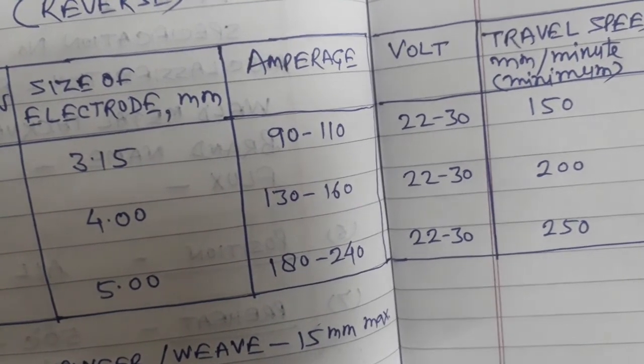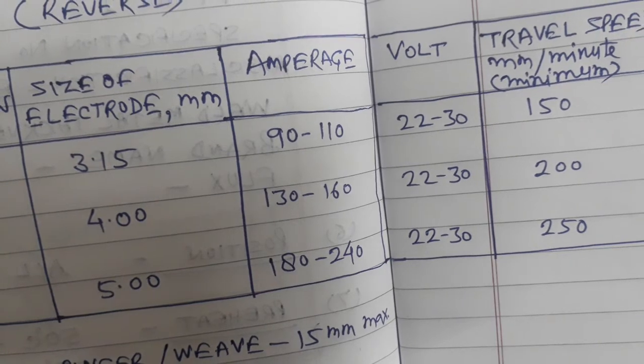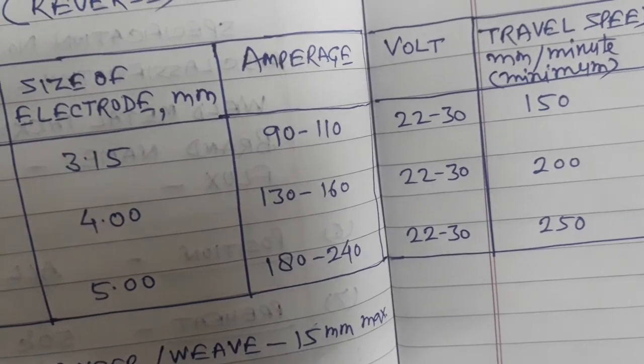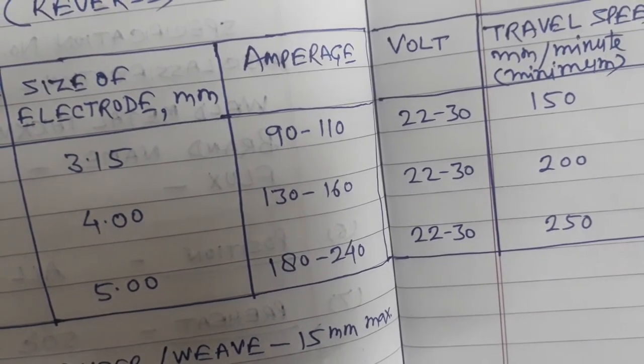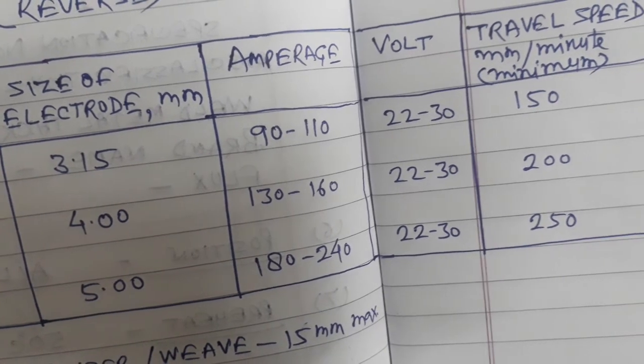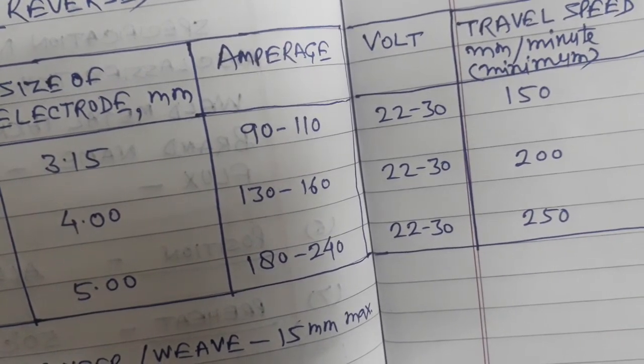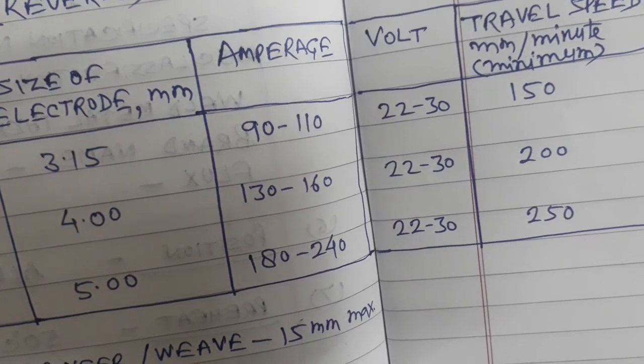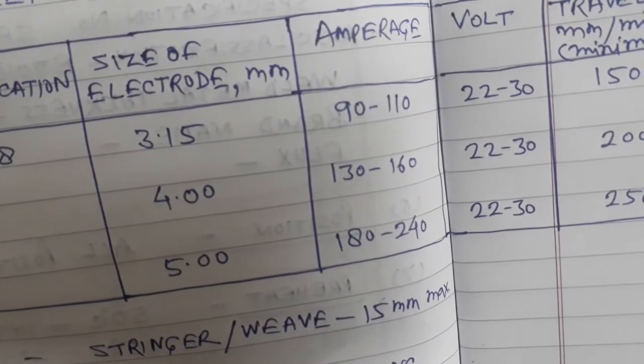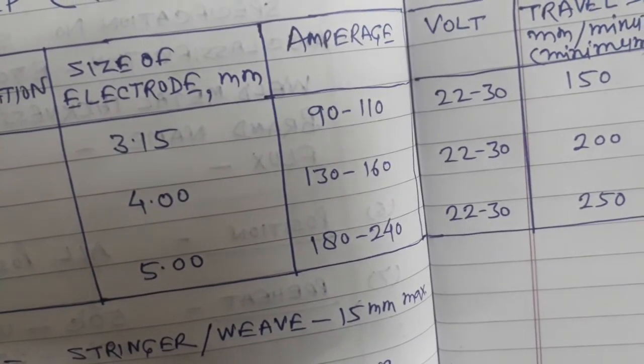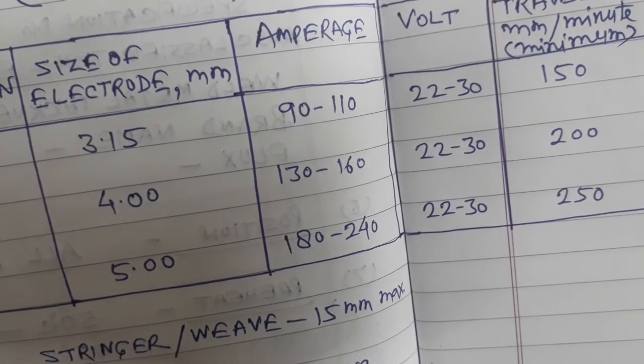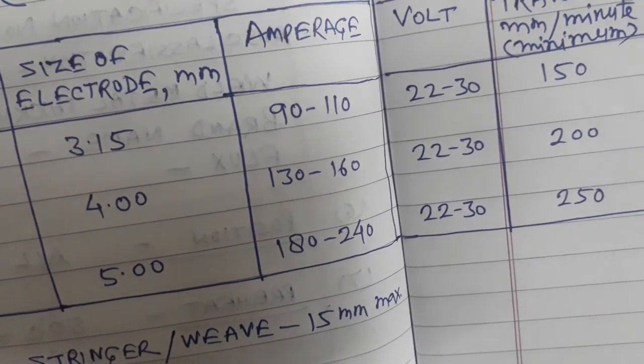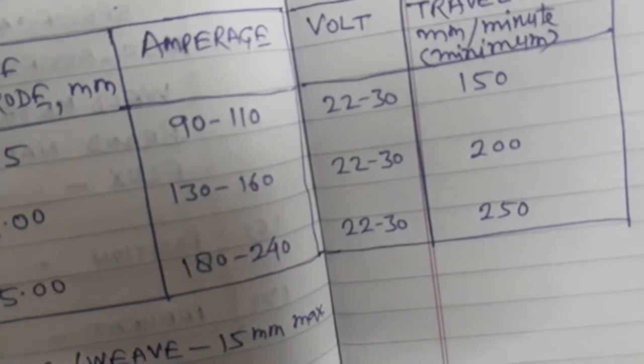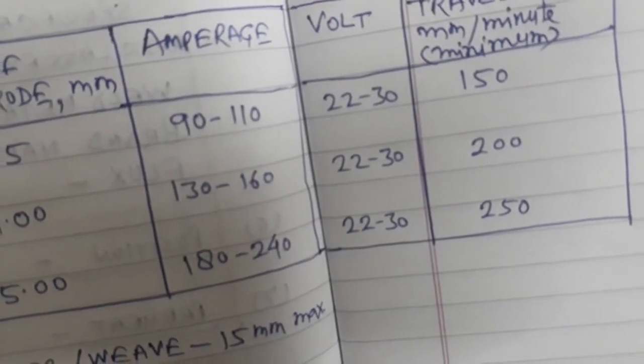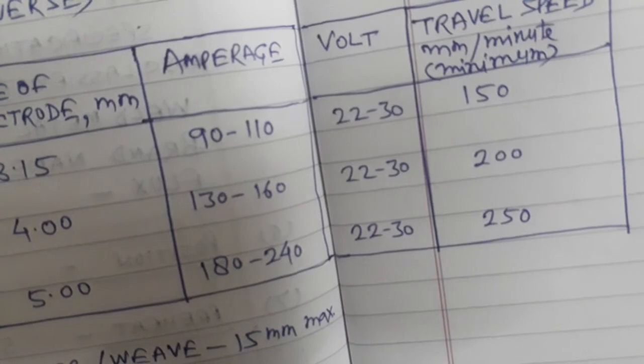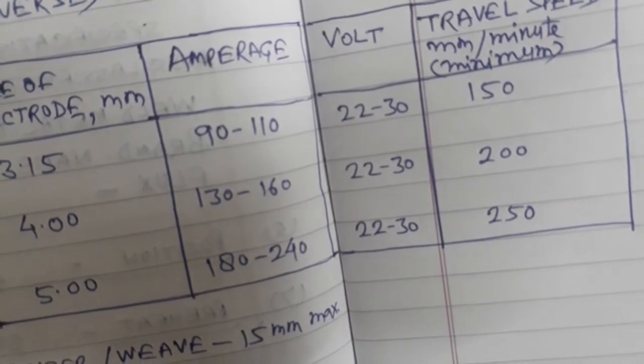Similarly, for a 4 mm electrode, amperage is 130 to 160, voltage is 22 to 30, and travel speed is 200 mm minimum. And for a size of electrode of 5 mm, amperage is 180 to 240, voltage is 22 to 30, and travel speed is 250 mm minimum.